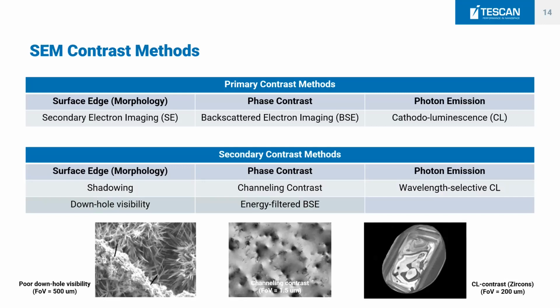It depends where you place your detector, and that affects the shadowing, and it provides you better visibility in the bottom of the sample. With the phase contrast, it's not just about telling apart two different materials, whether it's iron, aluminum, or some carbon material. It also can describe the channeling contrast, so that's crystallography, or you can basically use energy filtering to enhance some contrast, and photon emission also can be wavelength selective. So it's not that you would just describe the CL contrast, which you can see in the image on the right-hand side with the zircon, where you can see the zonation, but you could tell apart also different species of those materials using selective wavelength detection.